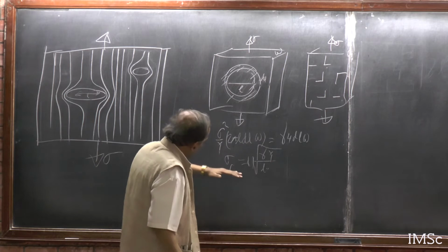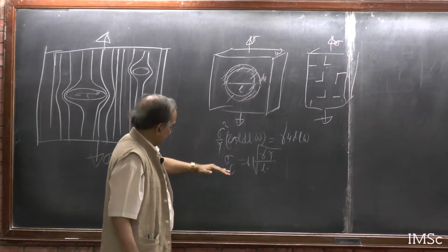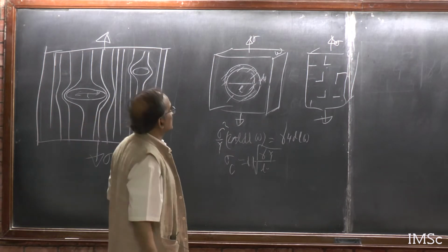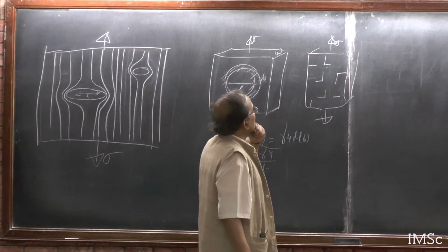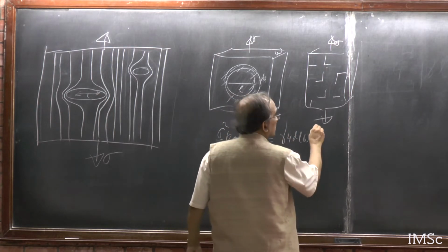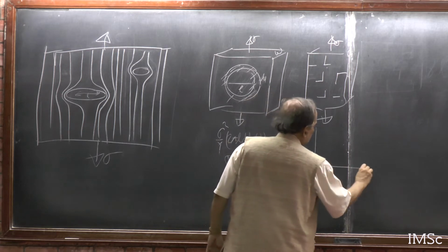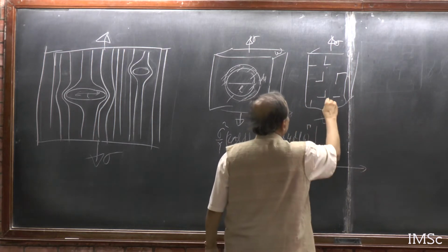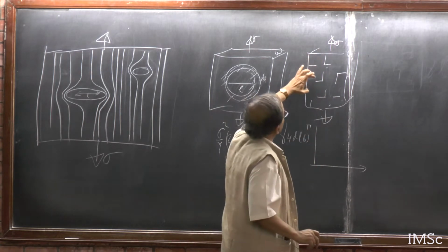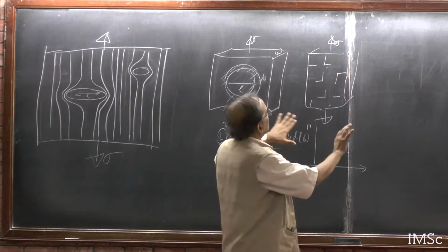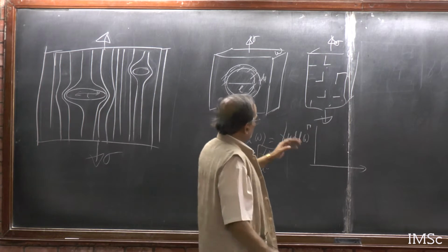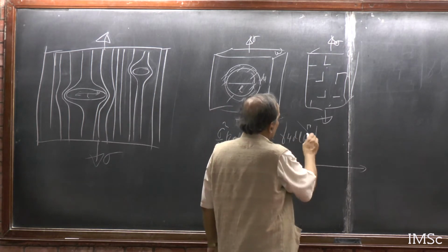Here you have a particular nucleation stress for the crack to propagate, and that will determine the strength of the whole system. Here you may not get that, and in fact I think phenomenologically people have studied for many years the failure probability in this kind of case. By the way, we still assume that the stress release regions are not overlapping, so in a sense they are independent.